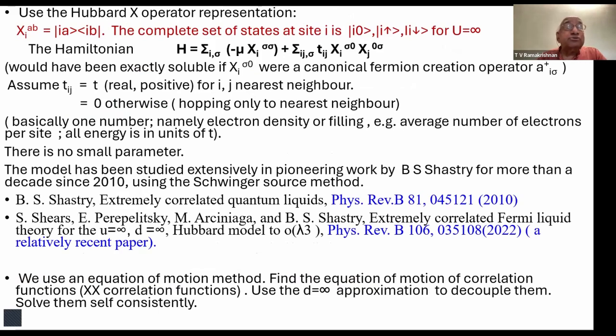To describe this limit, we use a very simple representation, which was again due to Hubbard, called the Hubbard X operator representation. Basically, at a particular site i, you have these Hubbard operators X_i^{ab}, where this operator is this ket times this bra. The complete set of states at each site is given by what a can be. a can be 0, meaning no electron at that site; up, meaning one up-spin electron at that site; or down, meaning one down-spin electron at that site.